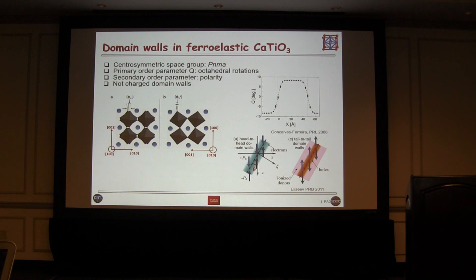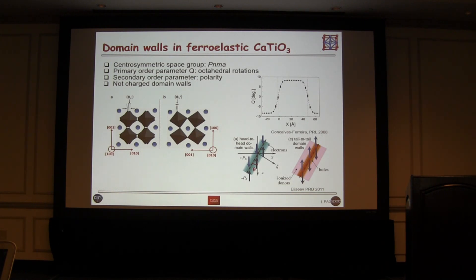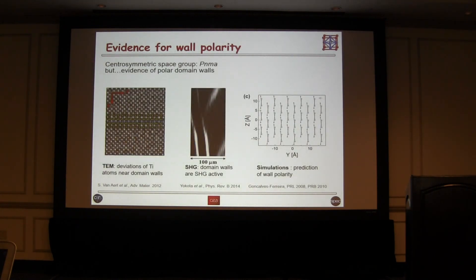Just to emphasize — sometimes we get confused about this — there's been a lot of work done on neutral and charged domain walls in ferroelectrics, and we're absolutely not looking at the same sort of phenomenon. The domain walls in calcium titanate are charge-neutral, and the polarity is in the wall itself. This is something I think is important to remember. There is off-centering, and you get a polarity along the domain wall.